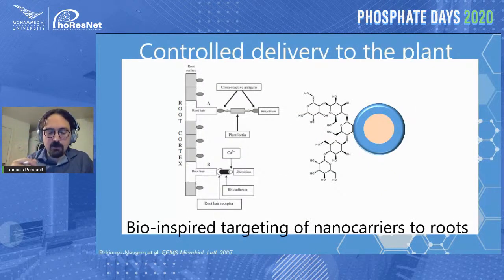Then moving forward, again, taking back our analogy with biomedical delivery, we can go from controlled release to controlled delivery. And this is something that we've been exploring in my lab in the past. We're trying to take inspiration from nature and look into these very specific interactions that you can have at the root surface using lectin binding sites, for example, and then engineer our nanocarriers to have very specific receptors. Here, this is a modified form of glucomannan, a carbohydrate that will specifically bind to that lectin to really enhance and enrich the root surface with these nanocarriers in order to achieve controlled delivery of that compound.